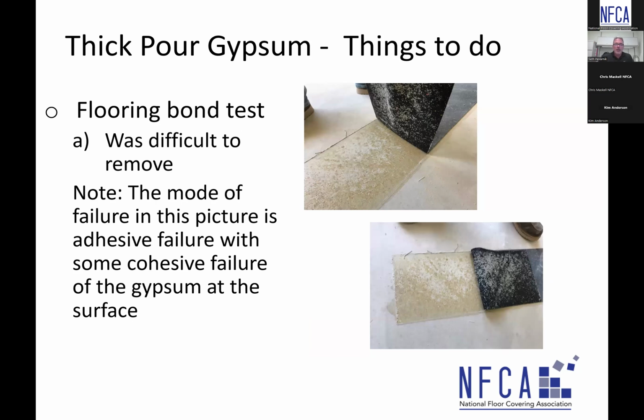So here's an example of the flooring bond test that was difficult to remove. And we're seeing cohesive failure within the adhesive. Sometimes you get a little bit of the gypsum, but the point being here, this was gypsum that was poured correctly. It was dry, it was properly primed, and we saw a very good result, the flooring being extremely difficult to remove.